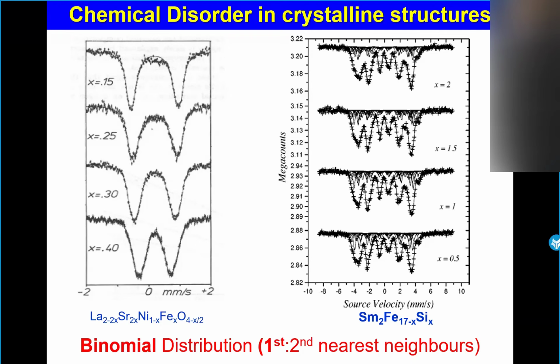In the case of the sextet, it's the same, for example for samarium, iron, silicon. And in this case, what it is possible to use is a binomial distribution. And afterwards, it's possible to describe correctly the different spectra with, I would say, a special attribution of the different components, and to see whether the disorder is homogeneous or not, in both cases.